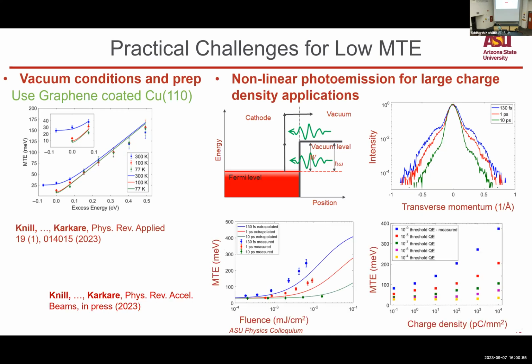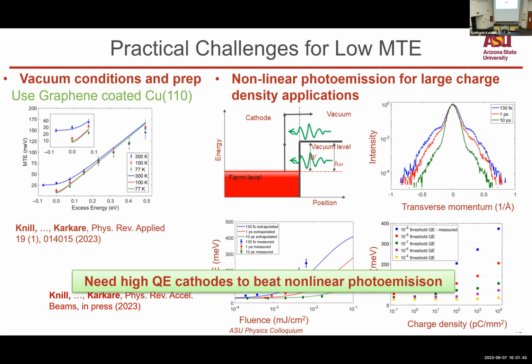And we were able to characterize the mean transverse energy as a function of laser fluence, and also get what mean transverse energy we could expect from this by extrapolation for various charge densities that are used in accelerators or used in some of these applications. And turns out, for the low quantum efficiency at threshold that we have, 10 to the -9 or 10 to the -8, for these large charge densities, the mean transverse energy goes back into this few hundred milli-electron volt scale. So to really be able to obtain these small mean transverse energies in these large charge density applications like X-FELs and colliders, we need to have cathodes which emit electrons with a very large quantum efficiency at the threshold. So we need high QE cathodes to beat nonlinear photoemission.